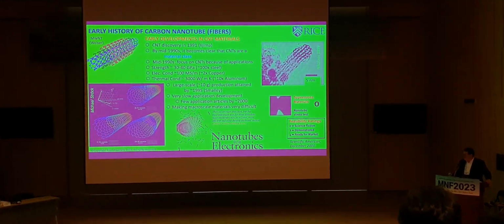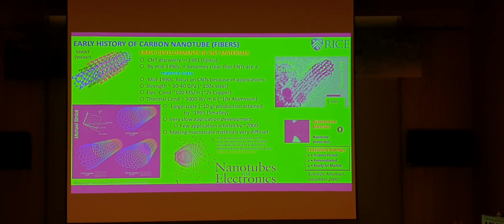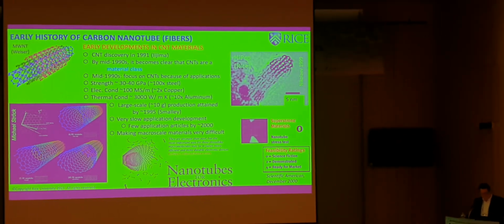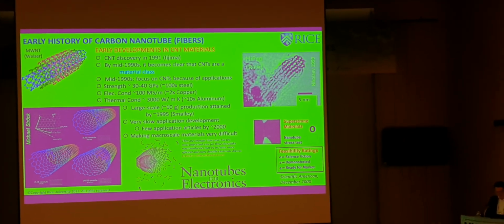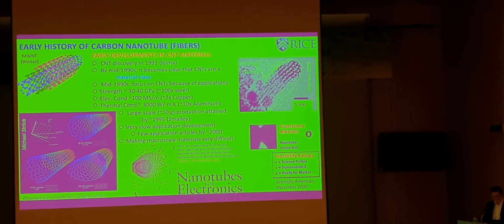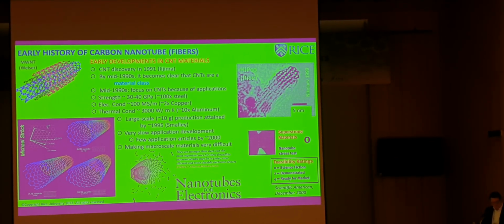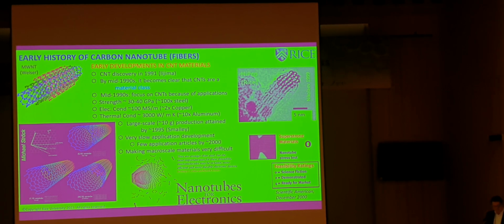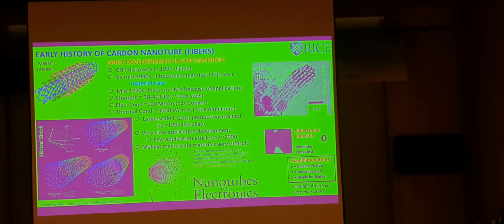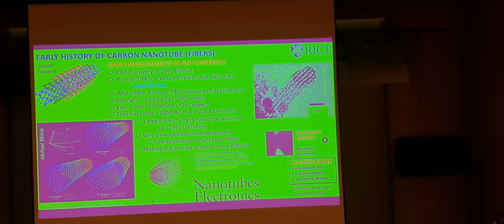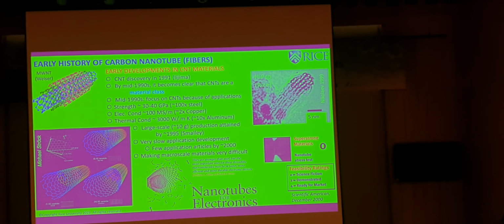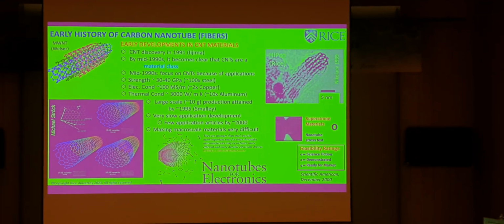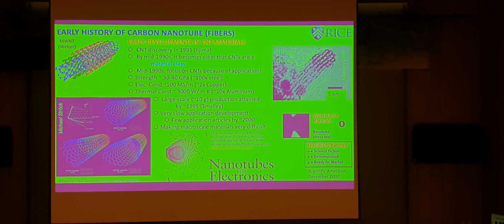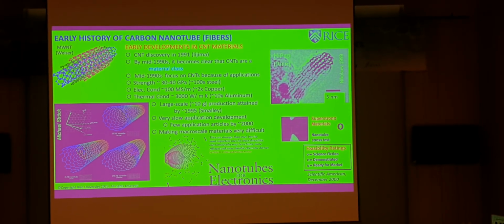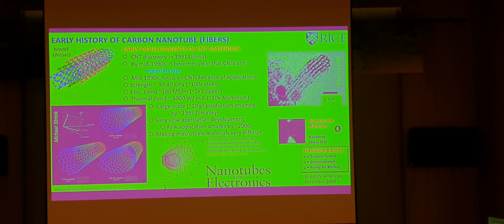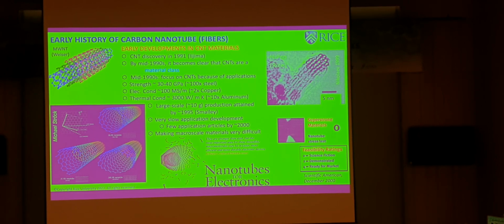So let me start. This is essentially the same slide that I used to start in Madrid, right? So, the discovery of nanotubes in '91. By the mid-90s, it's clear that carbon nanotubes are a class of materials. And people start talking about applications, and they start talking about strength in the tens of gigapascal, perhaps even 100 gigapascal, so 100 times stronger than steel, twice the electrical conductivity of copper, 10 times the thermal conductivity of aluminum, and so on and so forth.